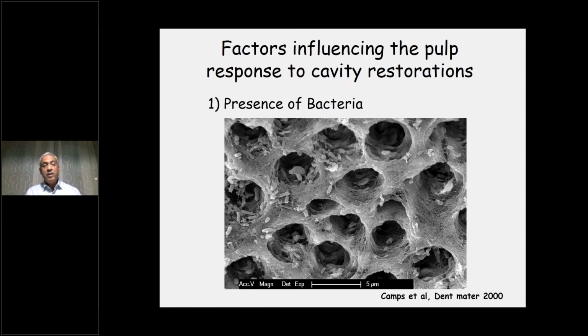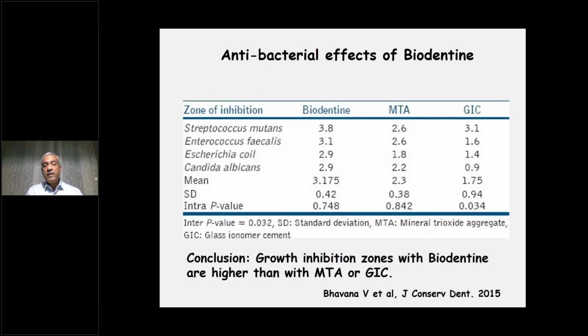When Biodentine was compared to other materials like MTA or glass ionomer cement, it was reported that Biodentine was efficient against several bacterial species. I can tell you that this is due to the alkaline pH, due to the hydroxyl ions that are produced. And these results are very important to provide an inhibition of bacterial growth once the material is placed.